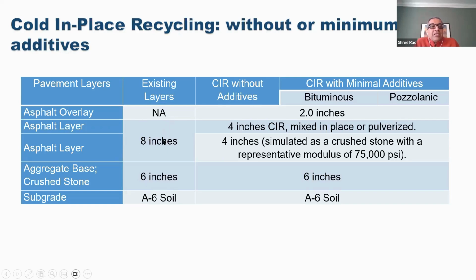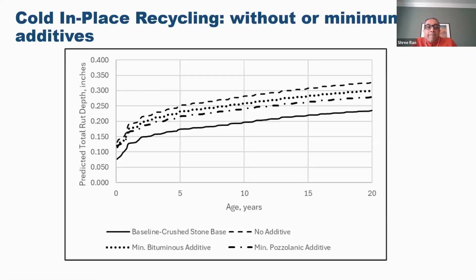Here's when you have an 8-inch asphalt layer over a 6-inch crushed stone base and subgrade soil of A6. You have cold in place recycle without additives, and then cold in place recycle with additives, and bituminous or pozzolanic additives. 2 inch asphalt layer, 4-inch cold in place recycle mixed in place, and then on top of the existing 4-inch, as I mentioned before, this is modeled as a crushed stone with a representative modulus of 75,000 psi in this case, and then here's your crushed stone.